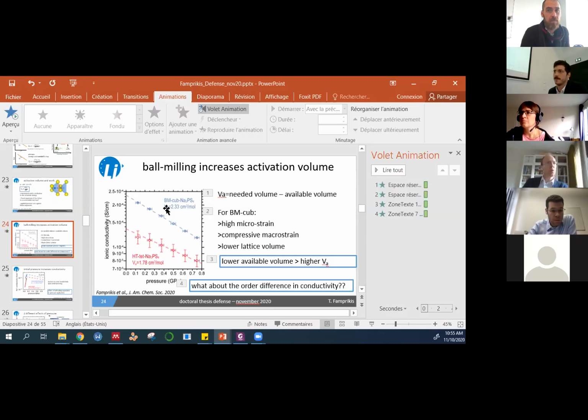But what if you cool these materials down to very low temperatures and measure the occupancies more accurately? So basically, you're using diffraction for compositional analysis somehow. Yeah, this is one idea, but I think if we really want to measure the composition, there are much more accurate and more straightforward analytical techniques. I mean, you can measure how much sodium is actually in your Na3PS4 sample through titration, through ICP, and so on. But I would say that's tricky if you have some glassy fractions. Yeah, it's true.